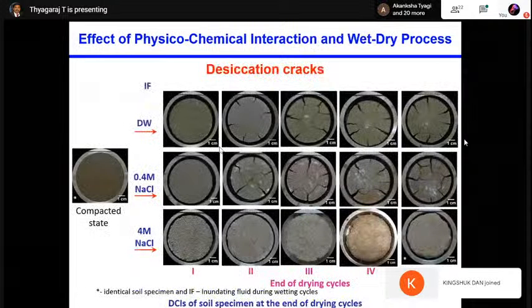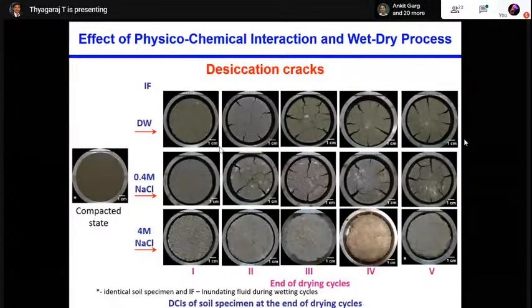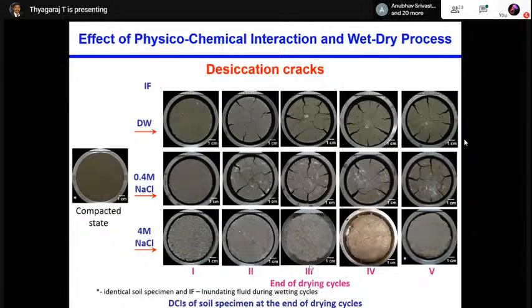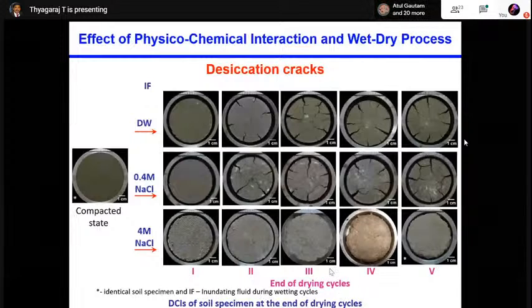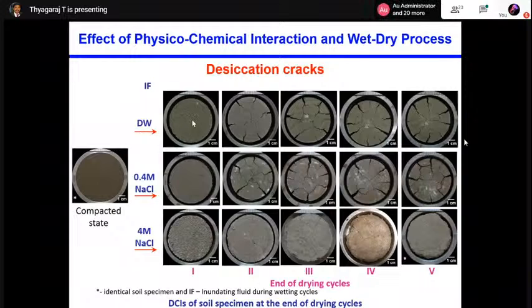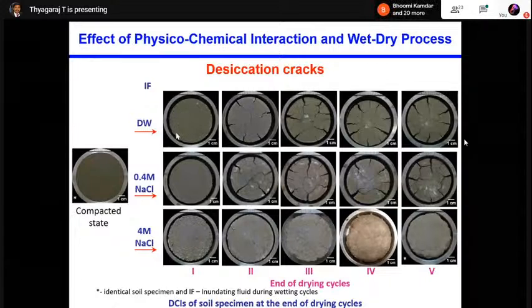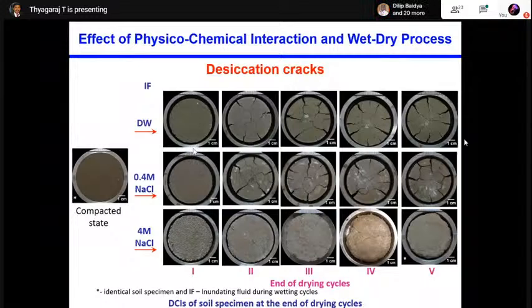Now, we wanted to further show what the images look like during different wetting and drying cycles. These images are mainly of the drying cycles. With distilled water, you can see that in the first drying there are no cracks. The same is true for all the specimens, for 0.4 molar and 4 molar NaCl solution. But during subsequent drying cycles, you can clearly see the cracks increasing. Not only the shrinkage, the cracks are also increasing.